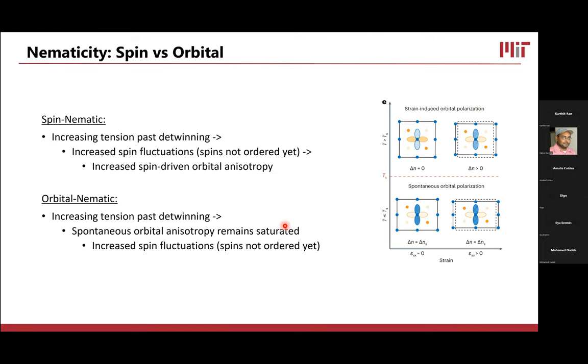So now, how does this fit into the discussion between spin nematicity and orbital nematicity? I want to lay out almost like a flow chart. We can come back to this in the Q&A. This is how I understand what I should see if I were to do this measurement under two different models. If I were in the spin nematic model, as I increase tension past full detwinning, I would expect to continue to increase the spin fluctuations.